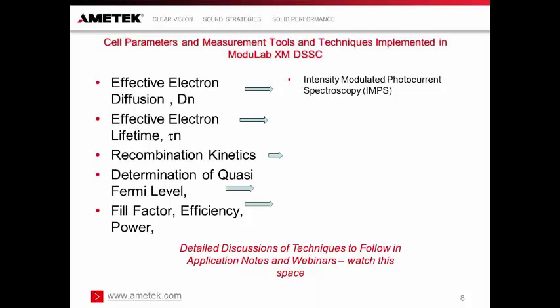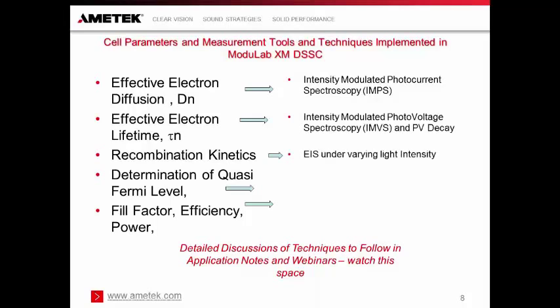Intensity modulated photocurrent spectroscopy for effective electron diffusion length, intensity modulated photovoltage spectroscopy and PV decay for effective electron lifetime. The recombination kinetics can be measured using impedance spectroscopy under varying light intensity. The determination of the quasi-Fermi level is facilitated by implementation of charge extraction techniques developed by Laurie Peter and the QFLS method, also developed by Professor Laurie Peter. And finally, we can measure the fill factor, efficiency, and power using IV curve measurements.